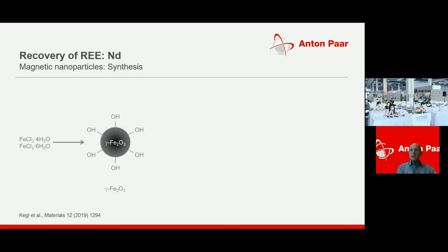The starting material for the preparation of the maghemite magnetic nanoparticles is a mixture of iron 2 and iron 3 chloride. By a co-precipitation method of these iron salts, followed by stabilization of the nanoparticles in ammonia solution, we first generate the magnetic core.